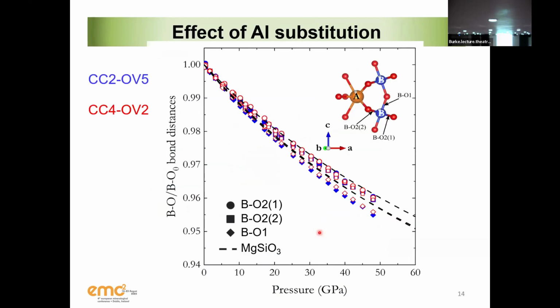But being a crystallographer, I also cannot not show some structural refinement. All these very minimal compression mechanisms we can see because we did single crystal. We could see the distortion of our perovskite at all pressures and temperatures. What we see here is a bit complicated, but I hope you will follow me. You have the individual bond distances of the octahedral site. BO21 and BO22 are the basal bond distances, and then there is BO1, the apical distance, which is the one along the C-axis.